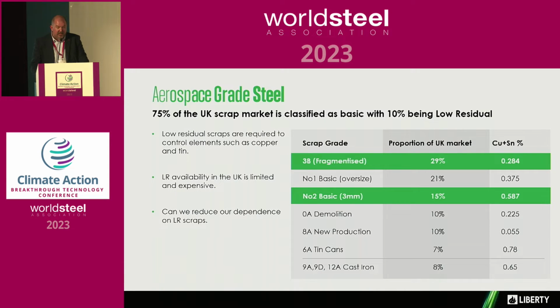Scrap processing, sometimes referred to as scrap cleaning, can reduce the copper and tin content of basic scraps, as some of the copper is not embedded and it's present only as components linked to the steel's previous use. These processes can vary in complexity, but all of them essentially liberate non-ferrous metals, leaving electric arc furnace operators with a cleaner, higher yielding scrap that is as low in tramp elements as possible. The more complex the process, the more non-ferrous material is liberated, and this has a twofold improvement. Firstly, the clean scrap can be used across more steel grades, and secondly, the embedded copper and tin levels are not increased.